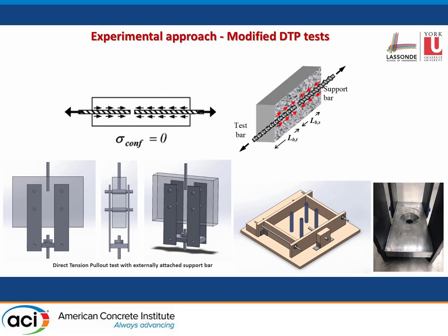So in the conventional method, the direct tension pullout has two bars embedded in concrete back to back on the same axis. One is the support bar, which has a longer anchorage length. The other is the test bar, which has a shorter anchorage length, the test length. And this has been modified because with the UHPC, you would end up with a very, very large specimen. So we developed a concrete block that is very thin in one direction. That thinness corresponds to the cover thickness that we want to test. In the other direction, the specimen is large enough to avoid tensile failure in concrete.